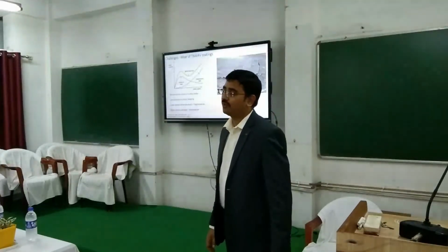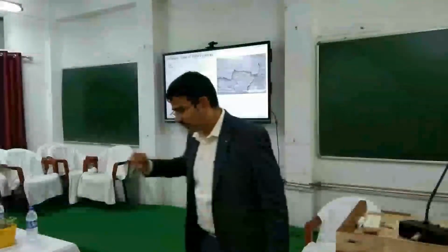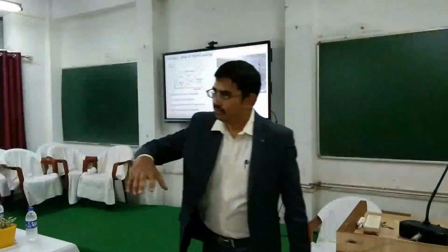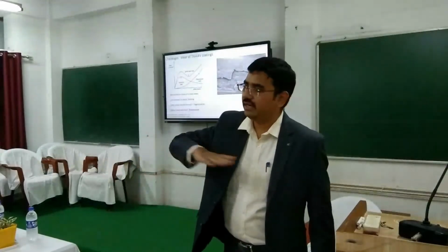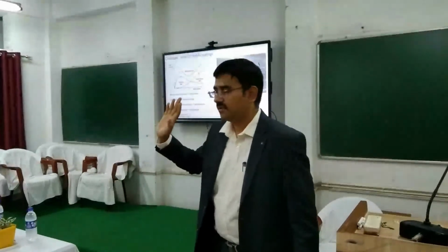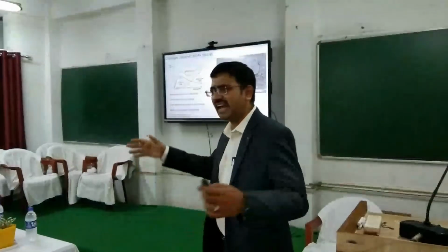Titanium components undergo extensive wear because of the non-protective nature of surface oxides. Okay, so we have two challenges. That is, one, to improve the tribological properties of titanium, and also to find a way through which we can get very dense deposits, because porosity in coatings is a problem. Especially then you have secondary mechanisms that come into the picture, that is fatigue, cracking, and coating delamination.